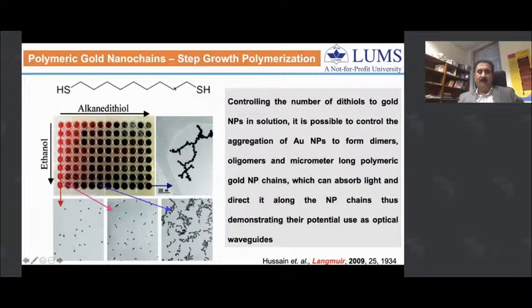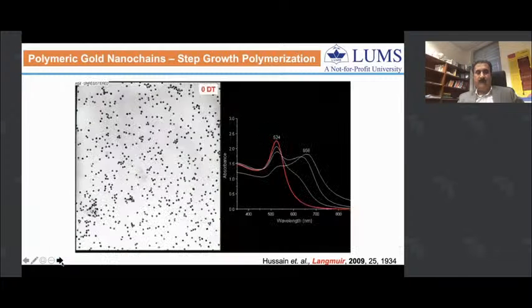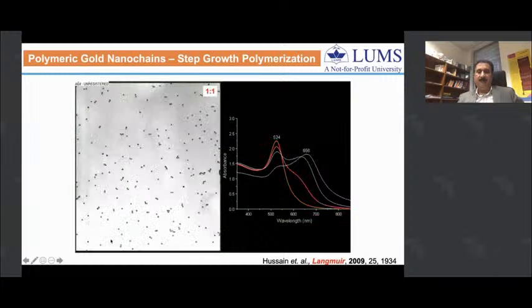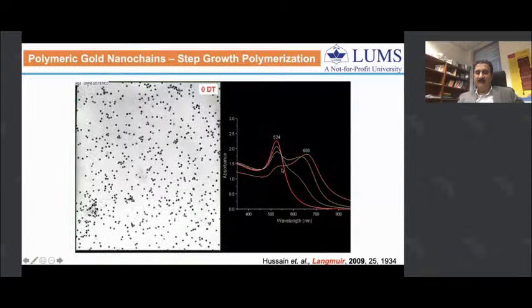added this linker. By controlling the amount of the linker, we were able to make either dimers, trimers, or even oligomers of these nanoparticles, and we can grow these nanoparticles stepwise. You will note that as we grow them, their optical properties change like this.